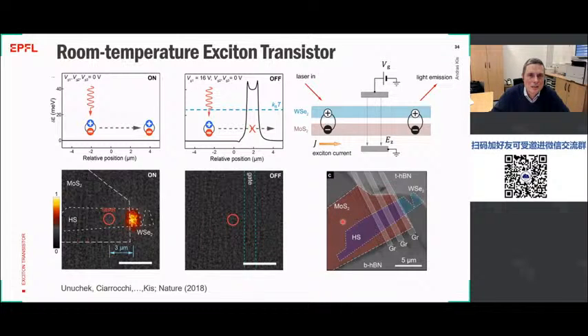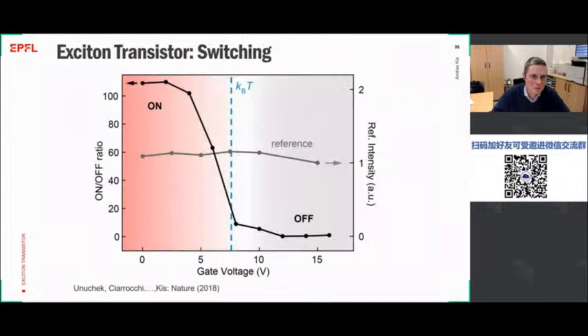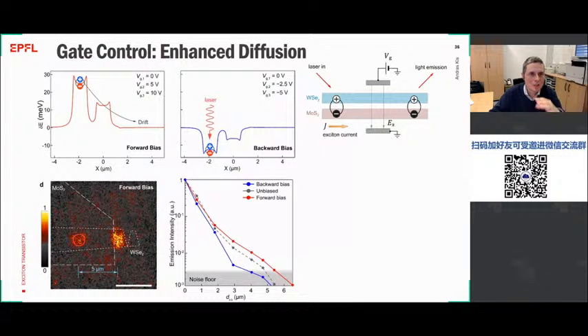So in this device, then we had excitons which were generated using a laser beam. They created the current and gave rise to light emission, which we could then modulate using electrical voltage. And we could also record a switching curve, which is in every way analogous to switching curve of a transistor, and we could have even an on and off excitonic current ratio. And we could not only switch the excitons, but we could also modulate a little bit their current. So by introducing a series of electrodes with a series of voltages, you could create something that looks like steps going down for excitons in energy or steps going up.